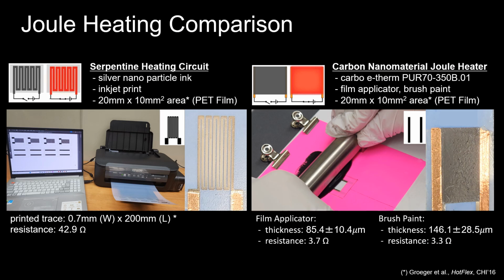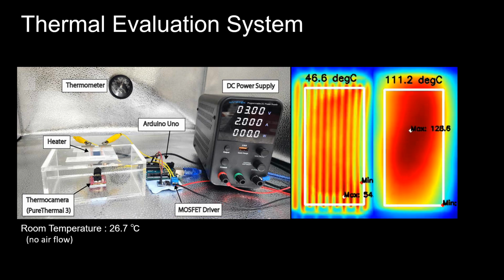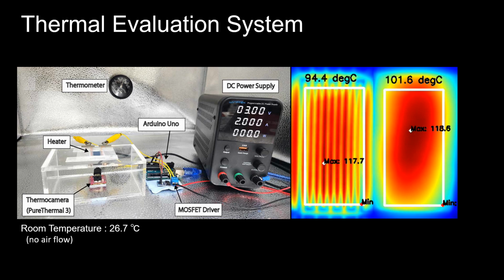We compare the thermal performance of the carbon nanomaterial heater with a conventional serpentine heating circuit. We made the sample heating circuit by printing PET film with silver nanoparticle ink. Heating paint was applied to the same PET film for a fair comparison, painted with a film applicator and brush. We measured the minimum, maximum, and average temperature of the 2 cm by 1 cm heating area with an Arduino-based heat control system and custom thermal camera image processing tools based on PureThermal 3. The experiment was conducted at room temperature without airflow.